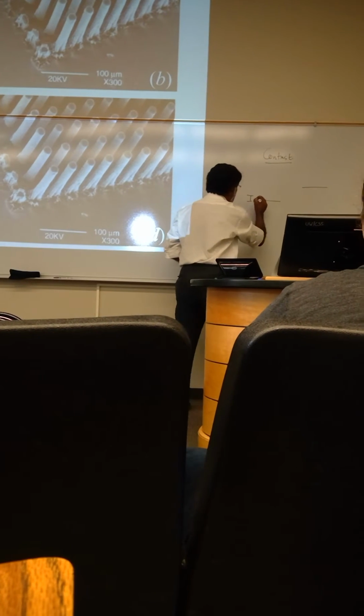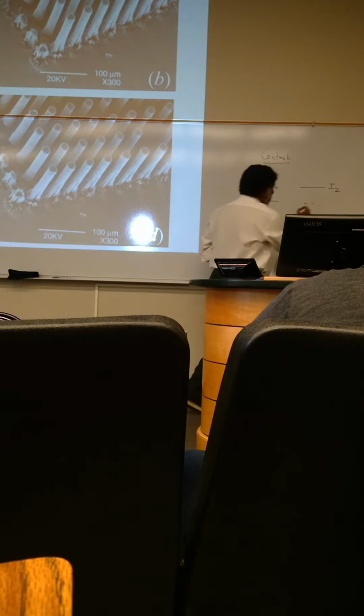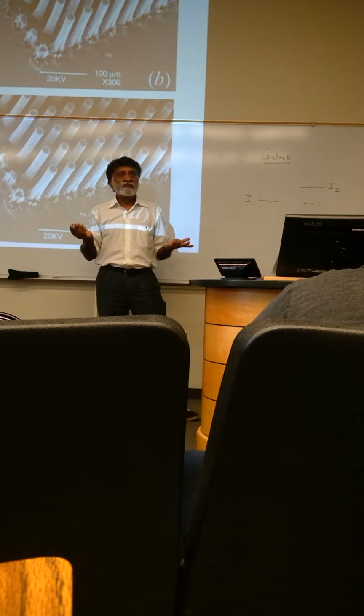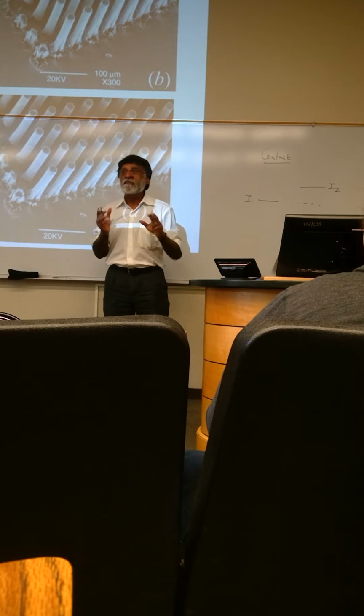You want to have a difference in intensity, I1 and I2. If I1 and I2 are the same, you don't have any contrast, because you can't distinguish in your image any difference between the two. So we're going to define contrast, which we call H, as I2 minus I1 divided by I2. This is your contrast.